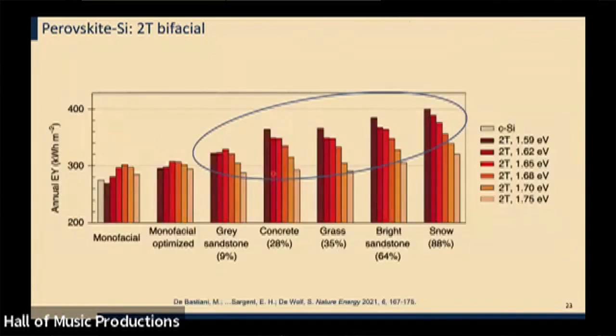But ultimately what these can do, you know, I talked about yield, which is my vertical axis here. Ultimately what these can do is they can achieve a relative increase of as much as 30% in the yield to solar energy flux that's accomplished in these tandem solar cells by levering the scattering and reflective properties of the underlying surface that the solar cells are installed upon through these transparent back contacts and through the re-optimization of the solar cell itself. And so it's these kinds of strategies that, again, are bringing us back towards these higher and higher efficiency cells that are lowering the cost.